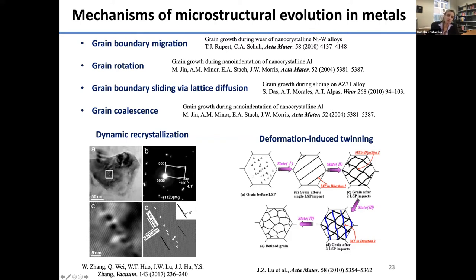Now, deformation-induced twinning applies only to certain materials that are able to twin. These are typically, for the material scientists in the room, materials that have low stacking fault energy. So copper is an example of that. Aluminum is the opposite. For materials that can twin, what can happen is that the twins can divide the large grains into smaller regions, and eventually these twins can develop into grain boundaries and refine the sample into smaller grains. So there are examples reported of that.